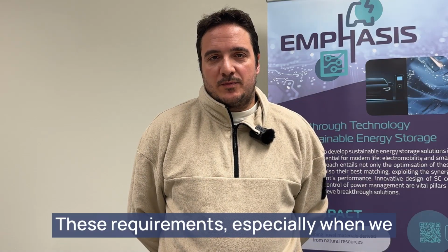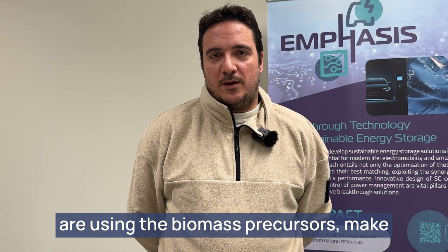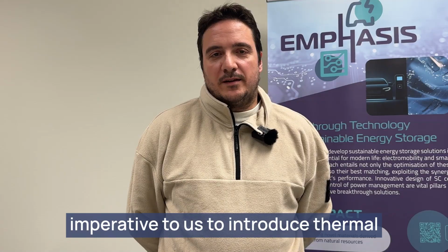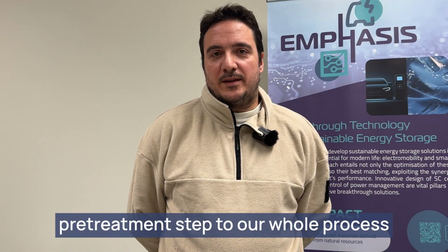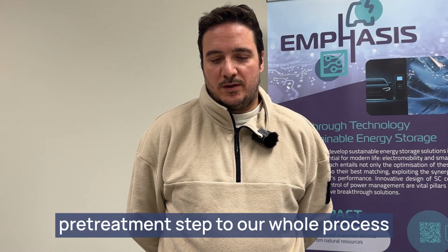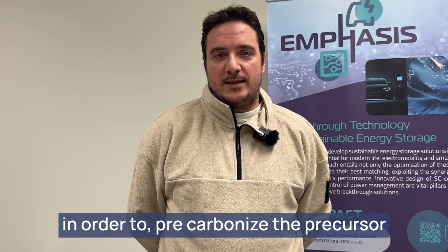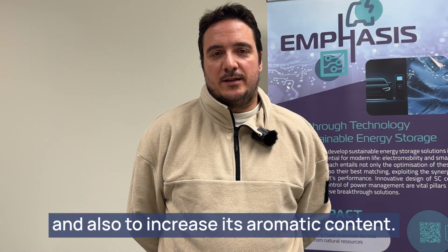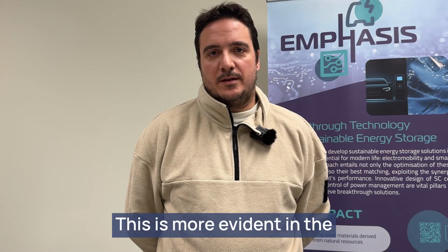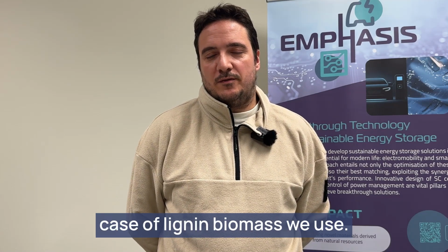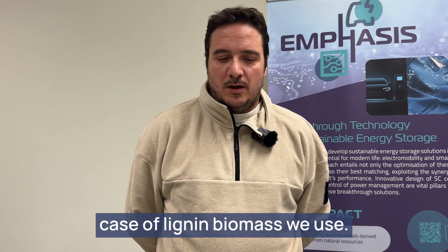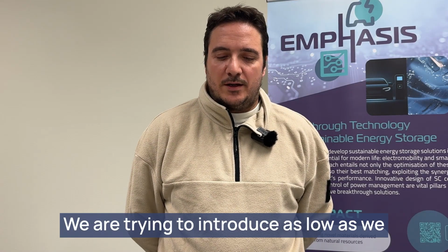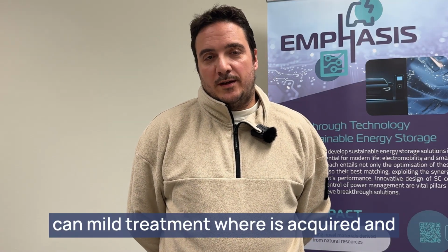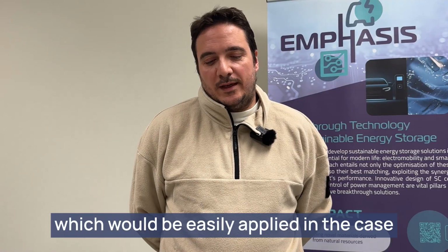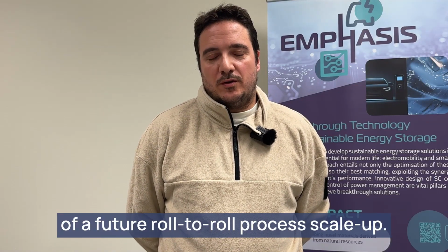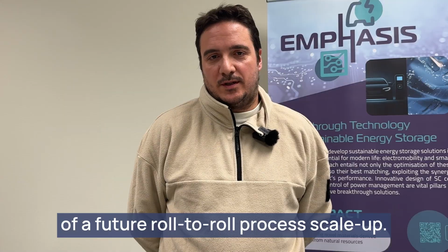These requirements, especially when we are using biomass precursors, make it imperative for us to introduce a thermal pretreatment step to our whole process in order to precarbonize the precursor and also to increase its aromatic content. This is more evident in the case of the lignin biomass we use. We are trying to introduce as mild a treatment as we can, where required, and which could be easily applied in the case of a future roll-to-roll process scale-up.